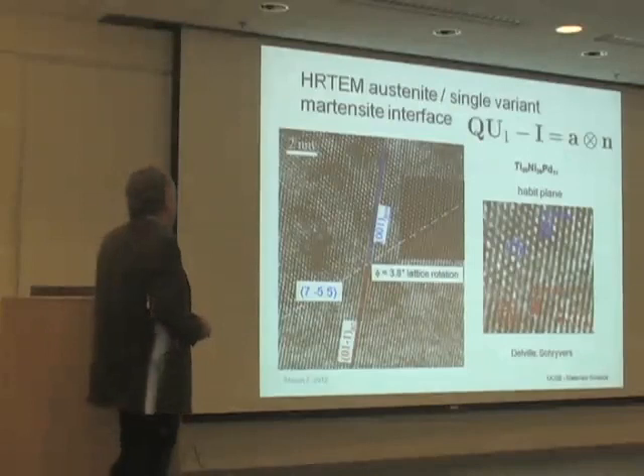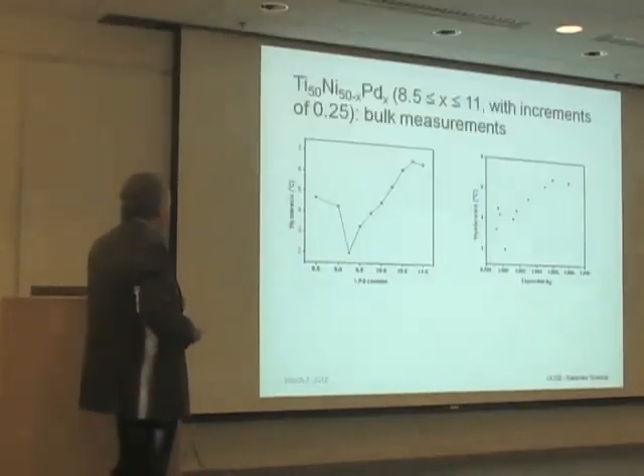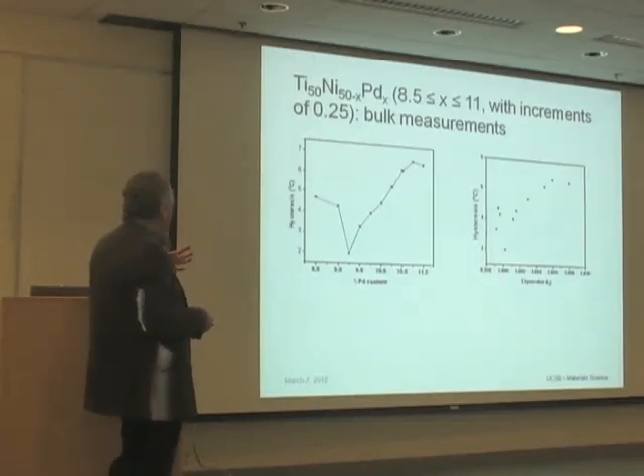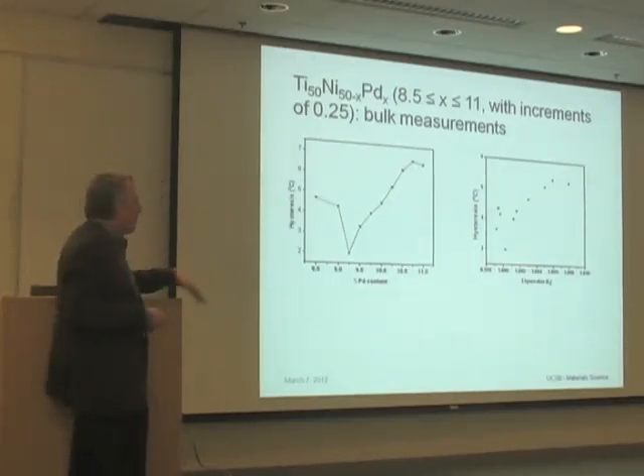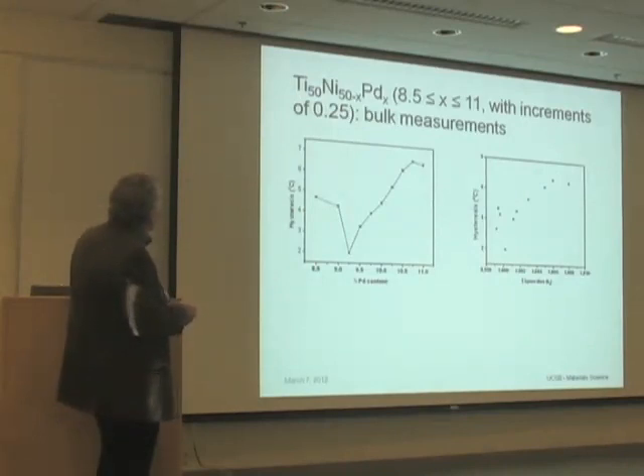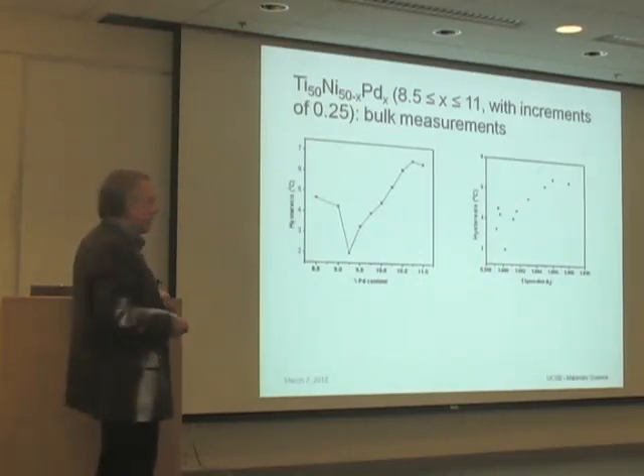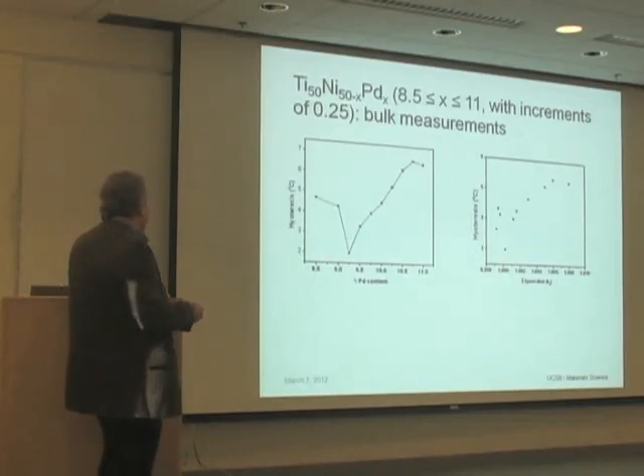So now in bulk, we wanted to try to get some of these extremely low, zero hysteresis alloys. So we worked in the titanium nickel palladium system, and we started varying composition, but we did it by quarter percent increments. So it was quite difficult, making a lot of alloys. And we found this was what we previously believed on the previous graph was the lowest hysteresis case. And we could actually reduce it to about 2 degrees hysteresis.